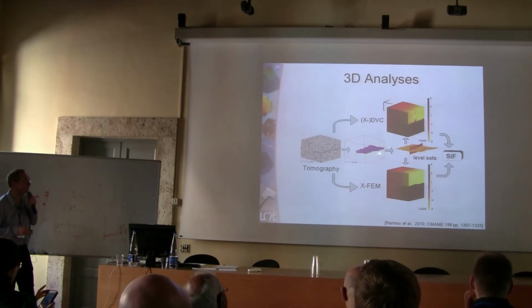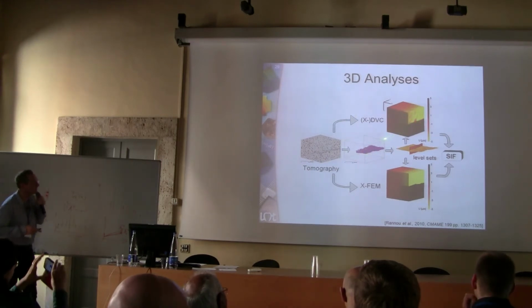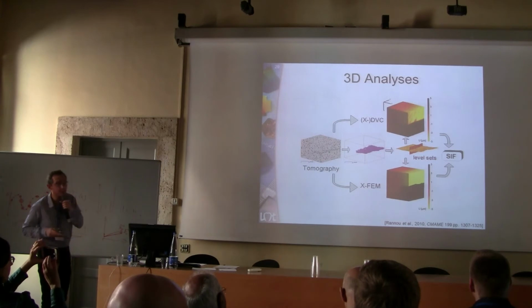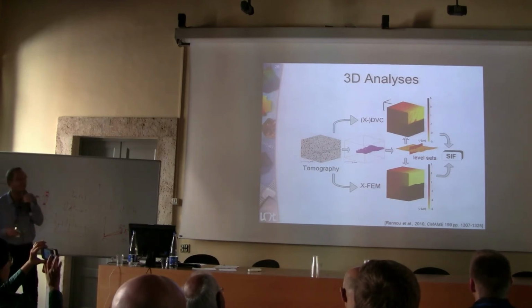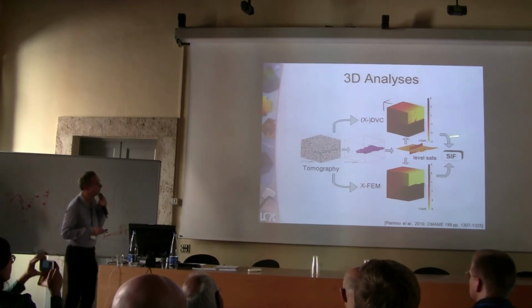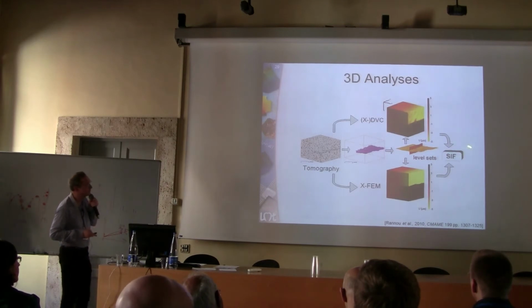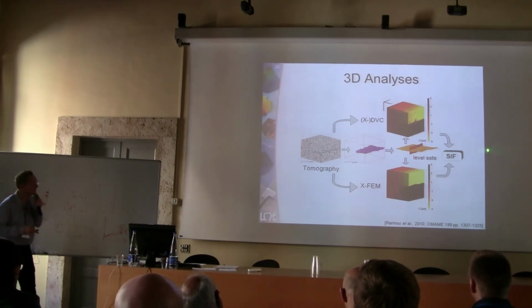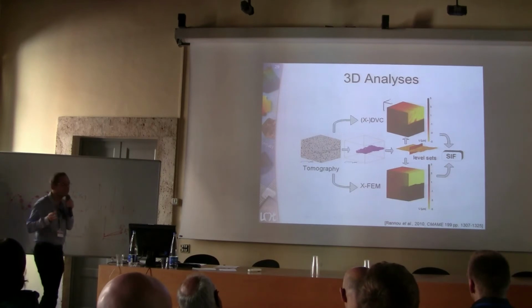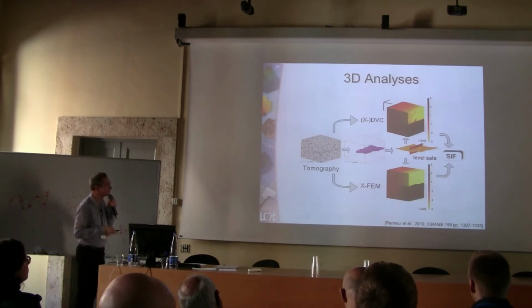You can measure displacements that basically obey the same hypothesis you would use in numerical simulations. From that you can extract stress intensity factors, and this extraction also allows you to construct the crack front.